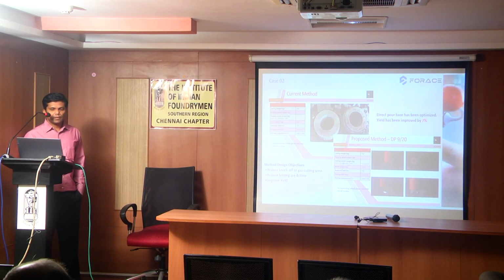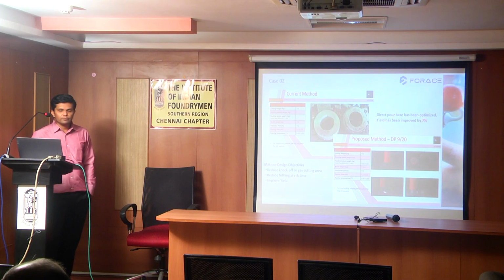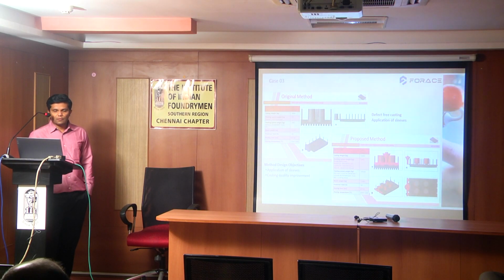Here also there is a direct pour case study where the customer asked us to optimize the yield. Because the casting weight is higher, we kept the direct pour sleeve as it is, and we tried to optimize the base, by which we got around 7% yield improvement. This is another case, where the customer had a problem: they were using outside sleeves or outside risers, so they were getting shrinkage in the casting. This is a 2-ton jaw plate type casting. There we have given the sleeves or solutions, and the castings are now okay.